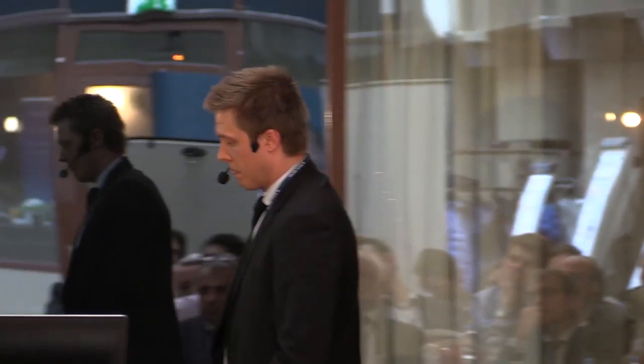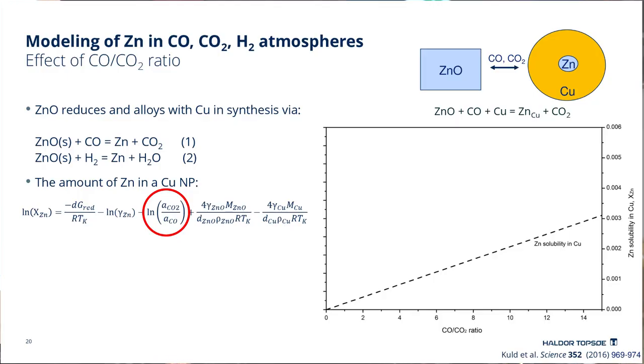So we started out with a model approach, and thermodynamically, zinc can form a copper and zinc bulk alloy in contact with synthesis gas. This can either go through the reaction with CO or through the reaction with hydrogen. Which of these two reaction routes is the dominant one will be determined by kinetics. But we constructed our experiment and the model so it would follow the CO route here.